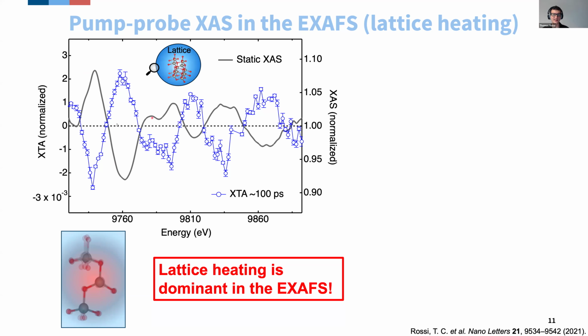The reason why it looks like a mirror image is because lattice heating basically increases the incoherent motion of the atoms in your system. By doing so, it's destroying the coherence of the EXAFS oscillations. There is a parameter quantifying this called the Debye-Waller factor. The Debye-Waller factor is simply a measurement of the mean square displacement of the atoms around the equilibrium position.